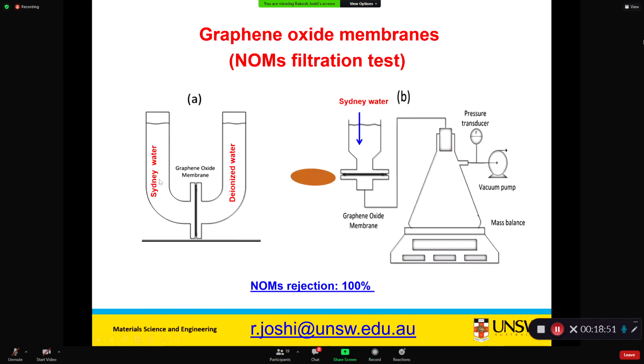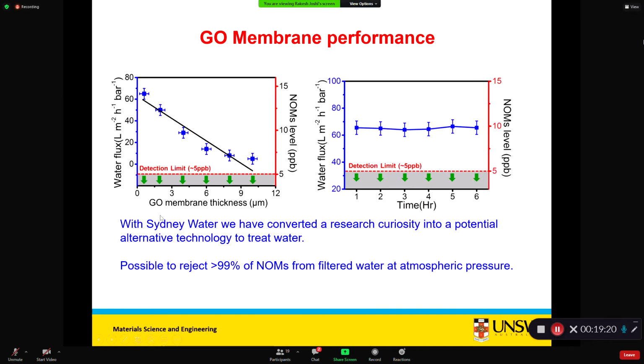Here, first I always do the tube experiment because this is the simplest one. It's Sydney Water's water and then deionized water, and then we measure the rejection, and then we do the same rejection using vacuum filtration, the flat membranes. At that time everything I used to do with flat membranes. Then we found that NOMs are always blocked using graphene oxide flat membranes, but if you really want to make membranes for industry, we need to make tubular membranes. And you see here, even with the flat membranes, we got a water flux of 60 LMH, and with good stability also. We can say we converted a research curiosity into an alternative technology, but this was not enough for industrial applications.